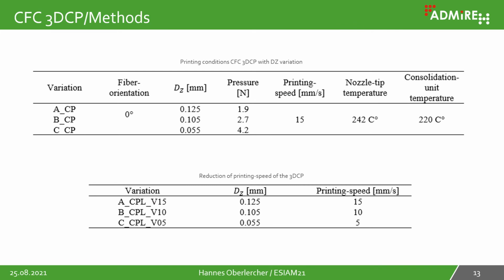With this 3D consolidation printer, we made two different experiments. The first experiment had three different variations, where we reduced the layer height and therefore increased the consolidation pressure: variation A to 2 Newton, B to 2.7 Newton, and variation C to 4.2 Newton. The printing speed was about 15 millimeters per second, the nozzle tip temperature about 242 degrees Celsius, and the consolidation unit temperature about 220 degrees Celsius.